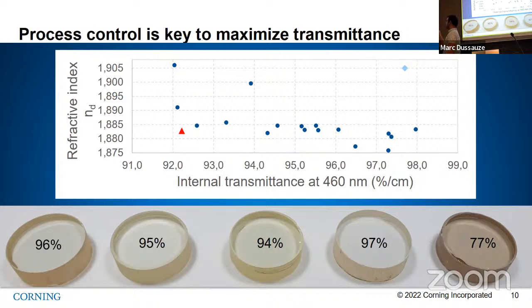So you see that the key, once you have the right composition, is to process it the right way to really achieve the best of the results you want to reach. And when we are able to combine all of that, I want to show you what we can achieve. So here on this plot, you see some data points from the lab, and in red you have the Corning 1.88 glass that was made